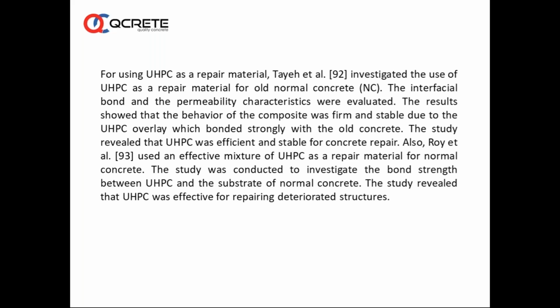So bridge decks, repairing of old bridge decks have been done. The study revealed that UHPC was efficient and stable for concrete repair. Also, Roy used an effective mixture of UHPC as a repair material for normal concrete. The study was conducted to investigate the bond strength between UHPC and the substrate of normal concrete. The study revealed that UHPC was effective for repairing deteriorated structures.